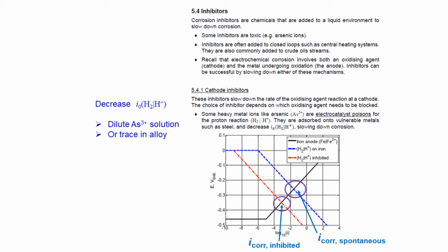The absolute key thing to remember here was that electrochemical corrosion involves an oxidizing agent, that's a cathode reaction, and the metal undergoing oxidation, that's the anode. Inhibitors can successfully slow down overall corrosion if either one of those mechanisms can be slowed down and made rate limiting, because they happen in series. So then, let's talk about slowing down the cathode reaction first, in section 5.4.1 on cathode inhibitors.